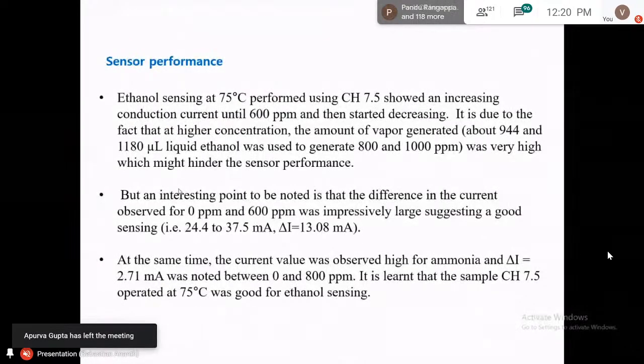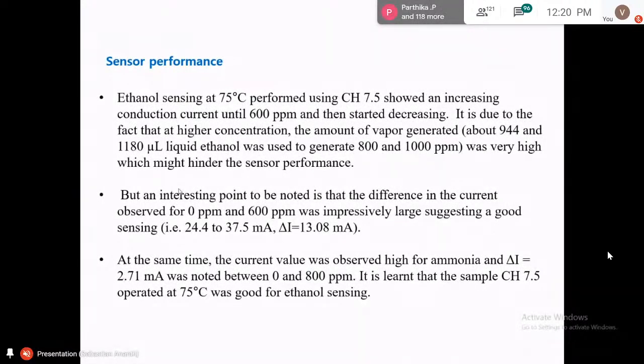So ethanol sensing at 75 degree performed using the CH 7.5 sample showed an increase in conduction current until 600 ppm and then started decreasing. It is because at higher concentration, the amount of vapor generated was very high, which hindered the performance because we are using the liquid form. If you use some other gaseous form, maybe the sensor may show a good response. But we use liquid form. That liquid started absorbing on the surface of the sensor, and then it is disturbing.